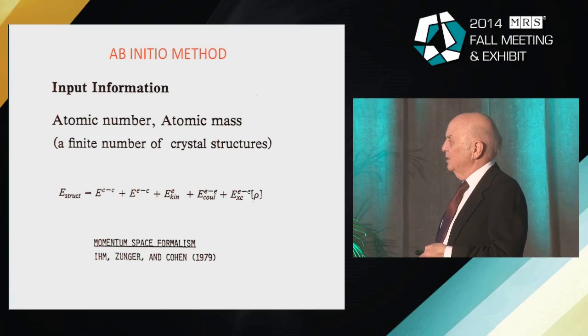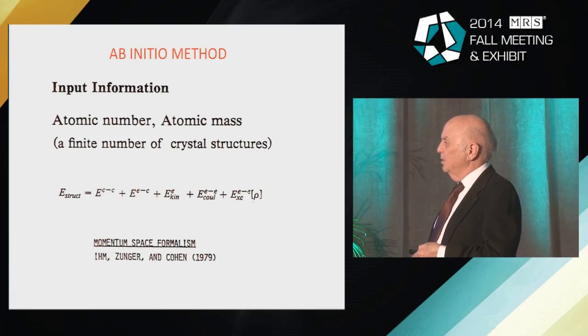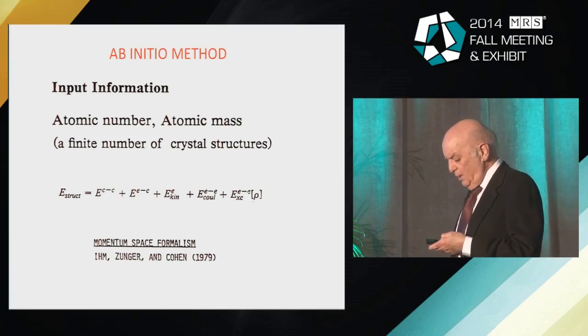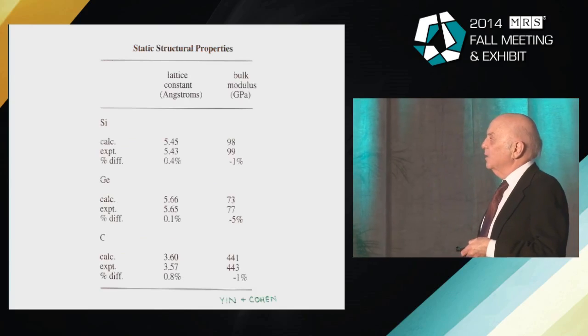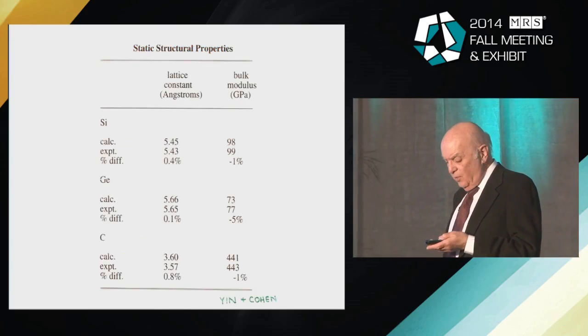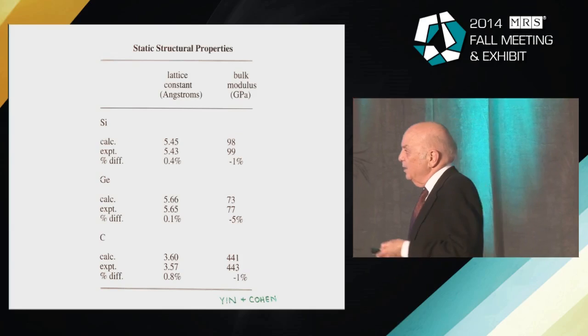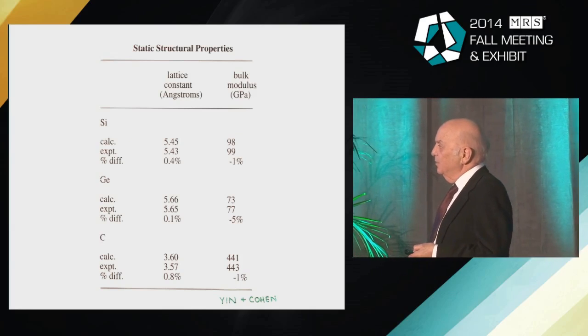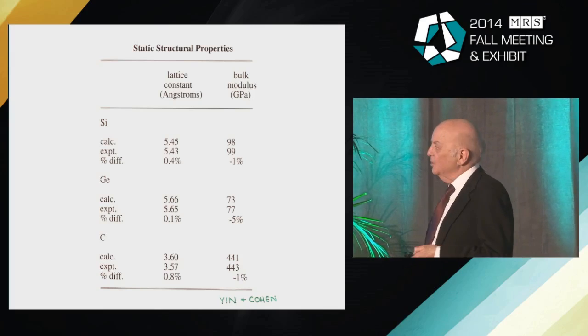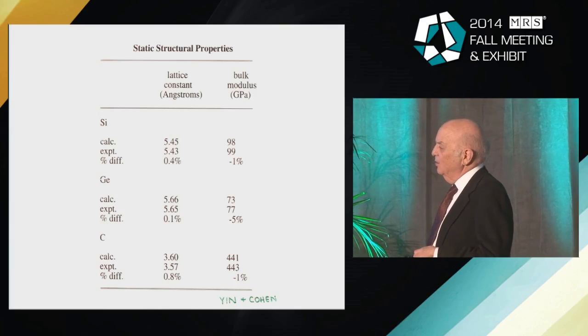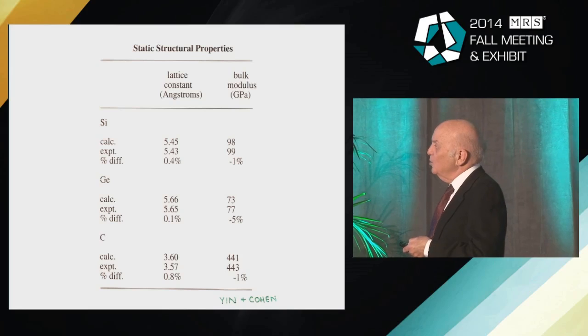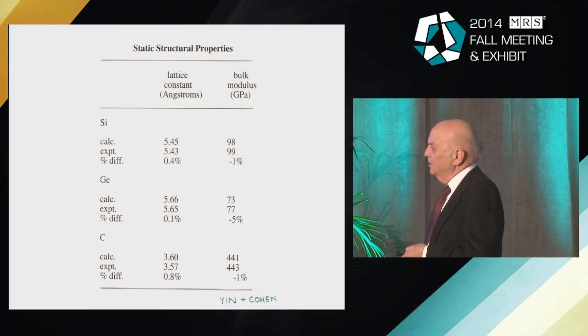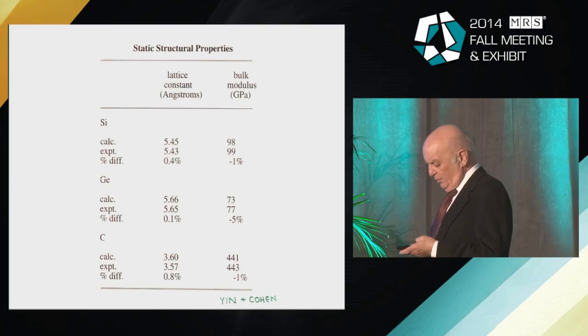The charge interaction, and then exchange and correlation, which people use density functional theory to calculate. If you do that, again, in this particular chart, this was the first one many years ago, the only input is the atomic number and the crystal structure. You can calculate from first principles the lattice constant to less than 1%, and usually the bulk modulus to less than 1%, but germanium is a sort of bad actor.